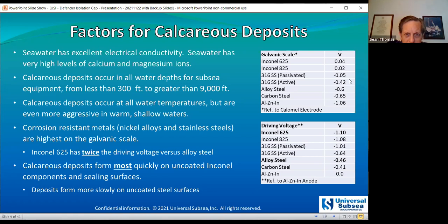The chart on the upper right of the slide is the galvanic scale for different metals. It measures the electrical potential for a given metal compared to a standard reference electrode, and the most common one is a calomel electrode. You see aluminum, zinc, indium at the very bottom of that chart, and Inconel at the top. The second table is referenced to the aluminum, zinc, indium anode. That gives us the driving voltage of the anode versus the other metals in the electrical couple. Carbon steel and alloy steel have a driving voltage of about minus 0.4 to minus 0.5 volts, whereas Inconel has a driving voltage of over minus 1 volt.